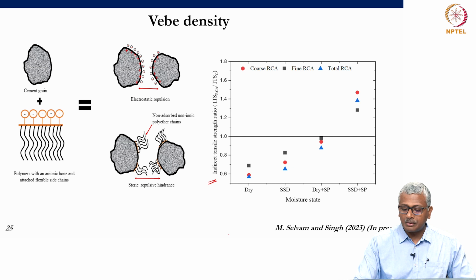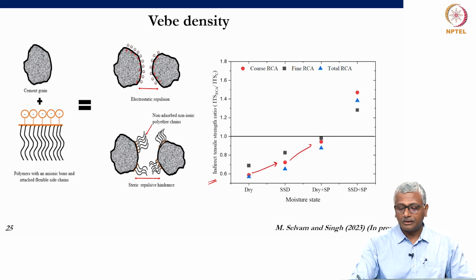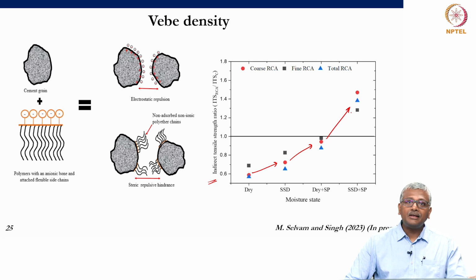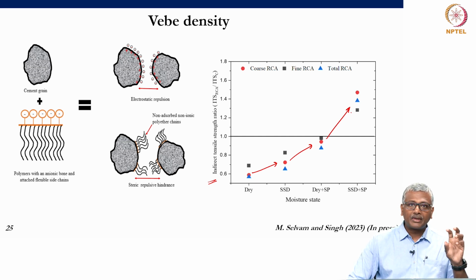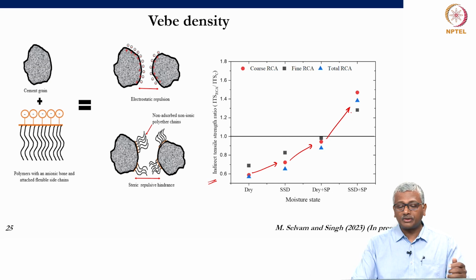So, you can see that as you are changing the moisture state from dry to SSD to dry with superplasticizer to SSD with superplasticizer, you are actually leading to a significant increase in your indirect tensile strength. And that shows that you can then really optimally design roller compacted concrete pavements with the help of recycled concrete aggregates when you take care of this SSD condition and also use a superplasticizer in your system. So, this effectively leads you to the fact that you can effectively design concrete mixtures with recycled concrete aggregate keeping in mind majorly the fact that the adhered mortar leads to an increase in water absorption, compensating for that becomes the primary target.